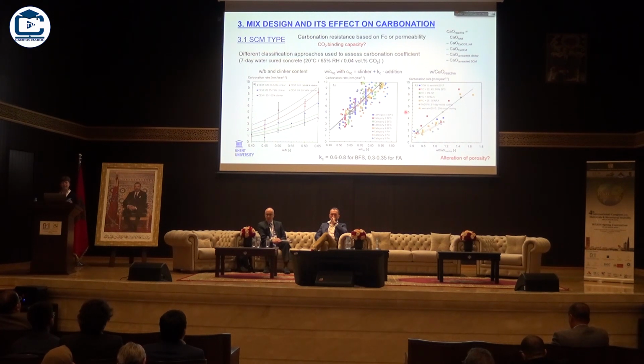Now, how do we relate or how do we express or study the carbonation resistance of mixes? Some authors base it purely on strength or permeability, but then of course you overlook the carbon dioxide binding capacity of your mix. So another way that it can be considered is to relate the carbonation rate, for instance, to the water binder factor and the clinker content. And then of course if you have too much water in your mix, you get increased porosity and increased carbonation rate. And then all these different curves, when they are higher up, it means that there is a lower clinker level, so you have also an increased carbonation rate because you have lower buffering capacity.